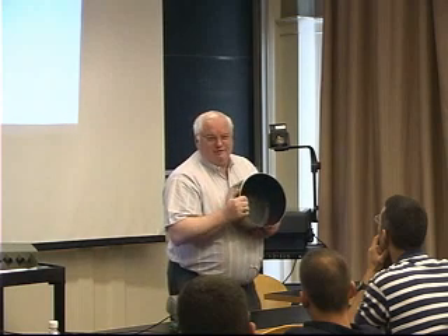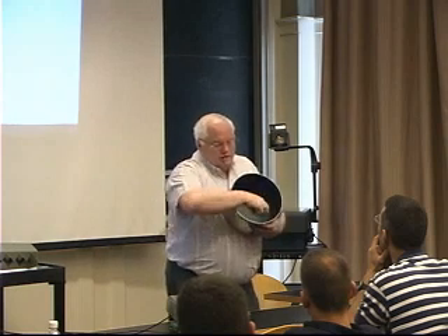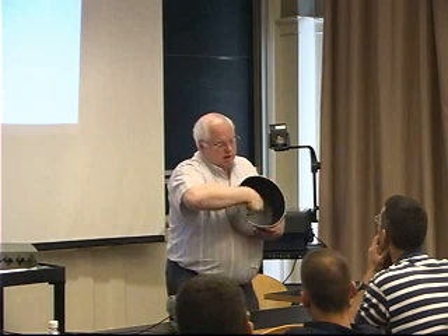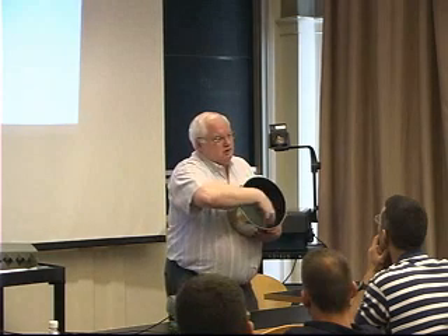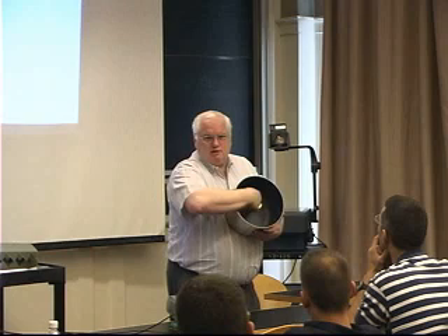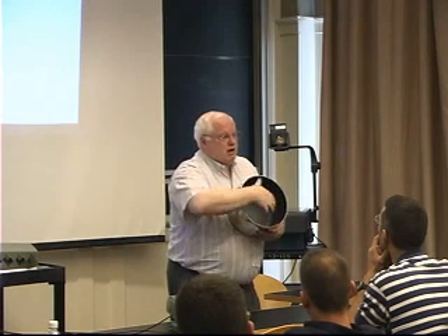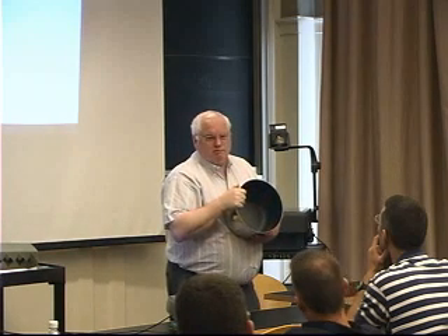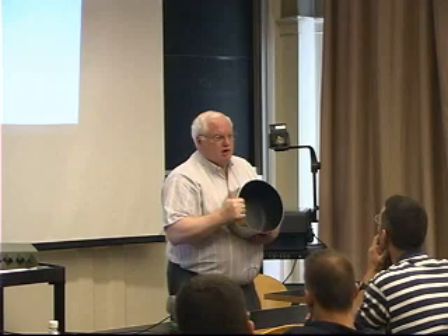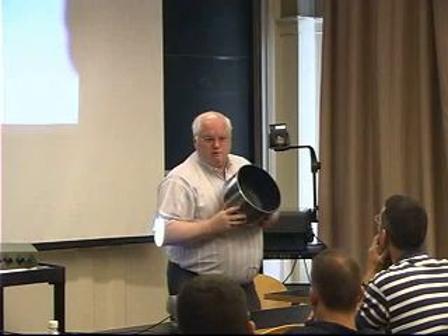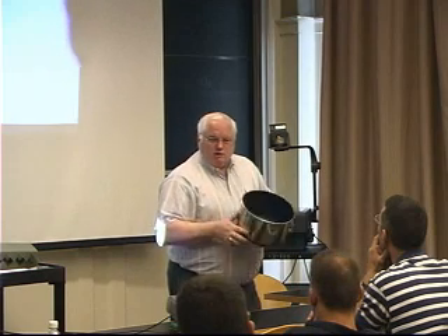I said, okay, well, you're going to have to. And so what they ended up putting on here is they plasma spray a porous powder of stainless steel inside this thing, and then they impregnate it with Teflon. So you get excellent bonding of the Teflon. You pay a premium price for this pot, and it'll crack on you because they got hydrogen in it.